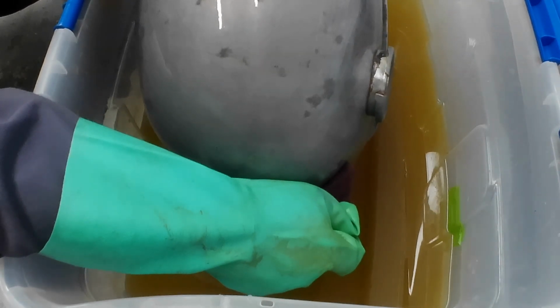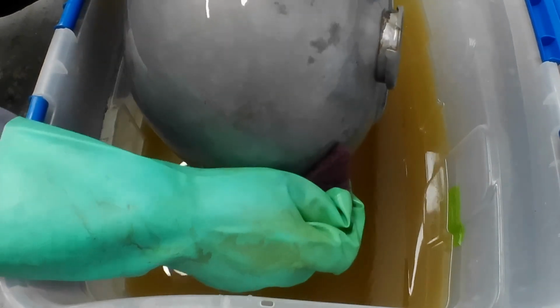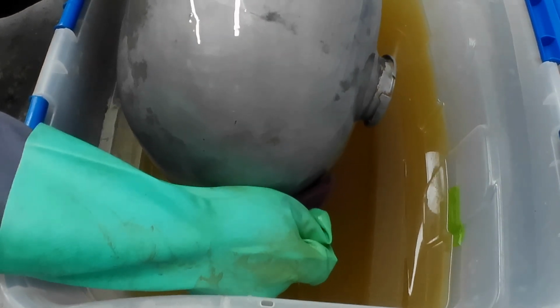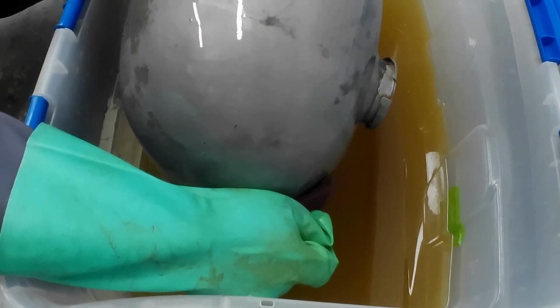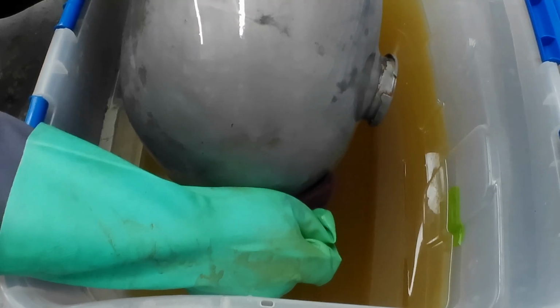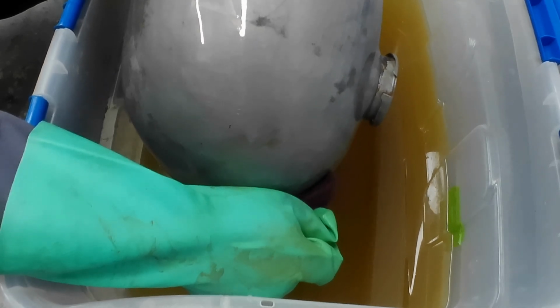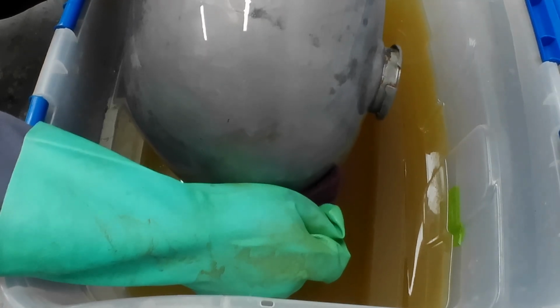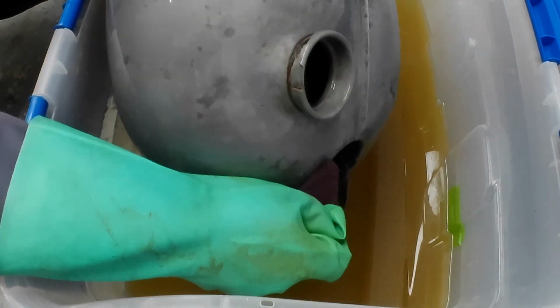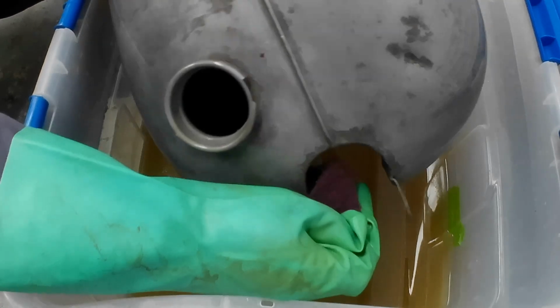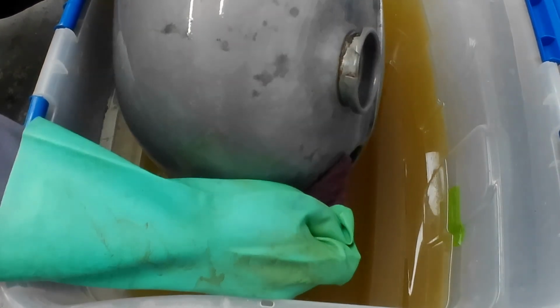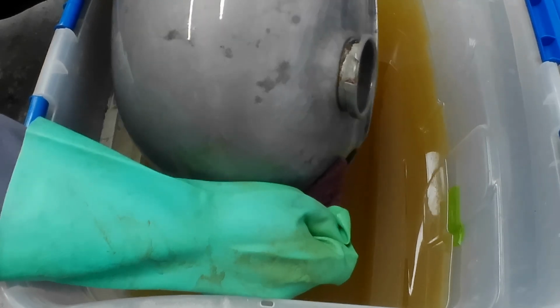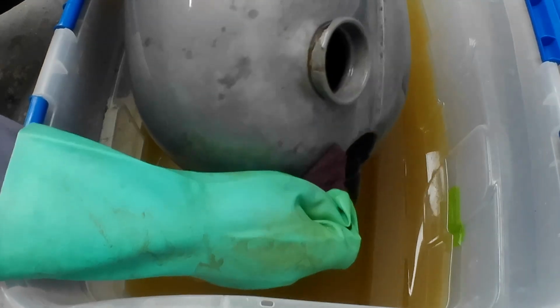And how you get rid of it is you heat treat. You basically put it in an oven for a period of time, and it off-gases the hydrogen. Higher carbon steels are more susceptible. I wouldn't do anything structural in this solution, something like a wheel spindle, even though, to be fair, most motorbike wheel spindles aren't particularly high in carbon anyway. I would shy away from doing anything life critical or safety critical, just in case you do get hydrogen embrittlement. But something like a fuel tank, it's not even a consideration. Wouldn't worry about it. So let me get that cleaned up and chase the moisture away with some methylated spirits, and then we'll get the boroscope out, have a look over at the bench, and it'll be on with the next phase of operations.